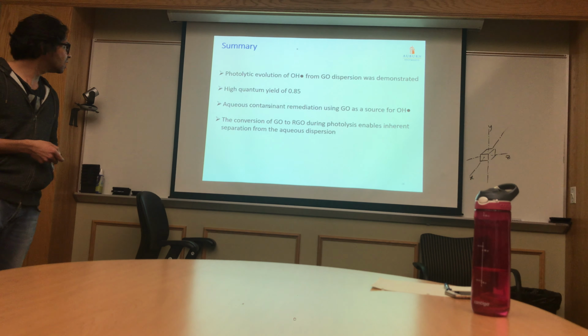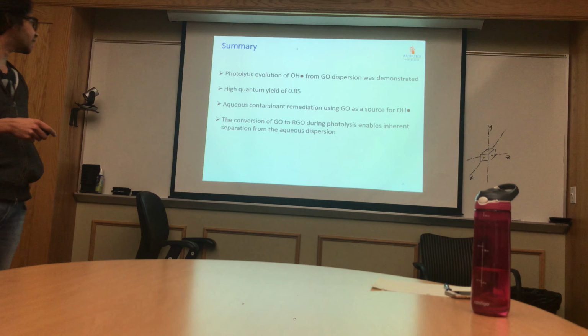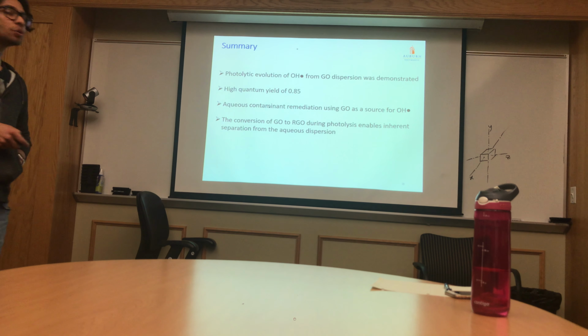So in summary, we showed the photolytic evolution of OH free radical from GO dispersion using the photoreduction method, and we achieved a high quantum yield of 0.85. We also utilized this method for the environment remediation, and the conversion of GO to RGO during photolysis also enables inherent separation from the aqueous dispersion.